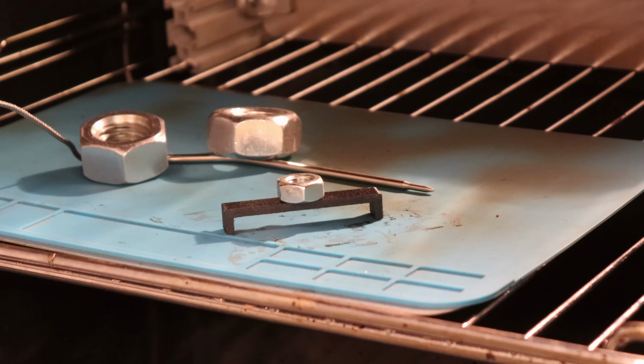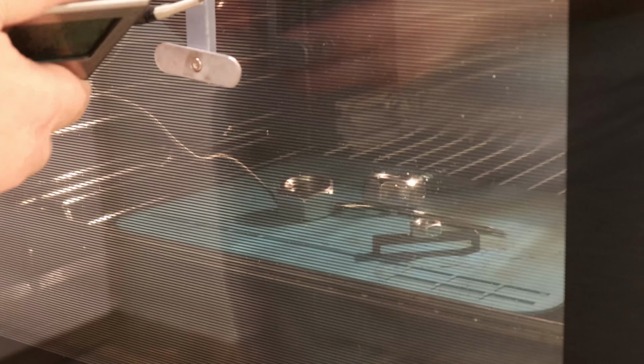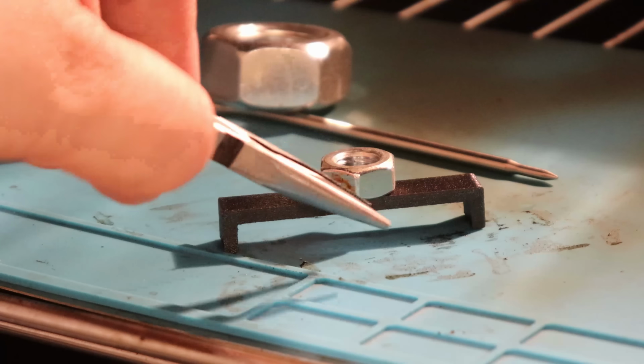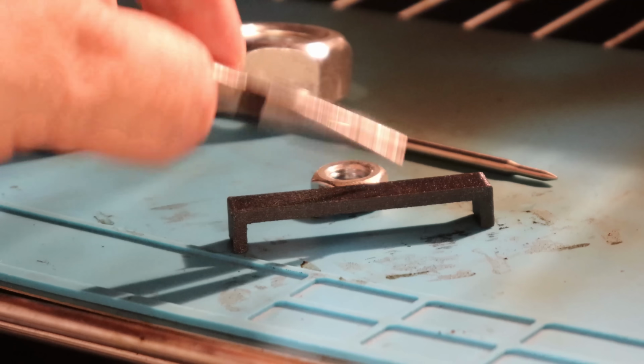Temperature test in the oven, and probably I will reach the maximal temperature of my equipment and there will be no deformation, but let's give it a try. I jumped in the time and this is the end of that testing. And I stopped the experiment at 230 degrees Celsius. And I checked the hardness of this test object, it is completely okay. Probably we can even operate at this temperature.